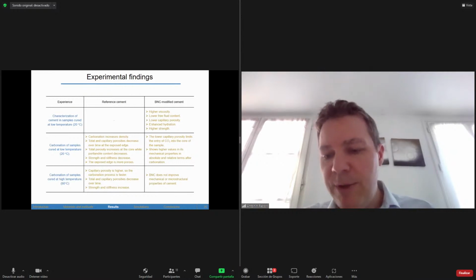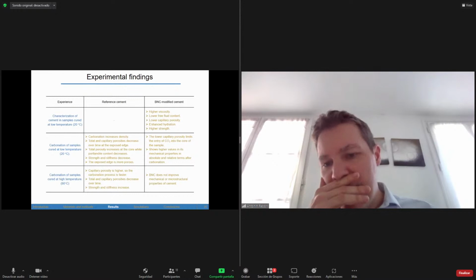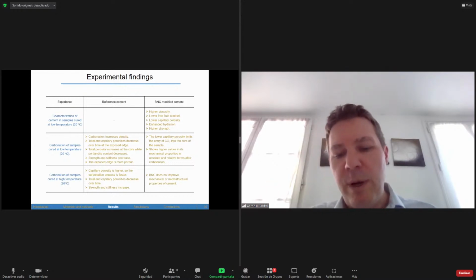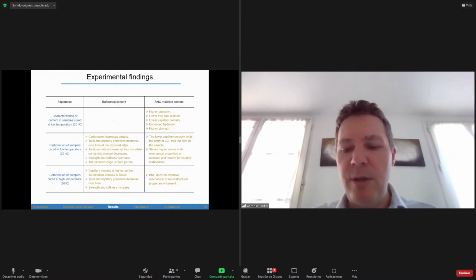But I don't understand two things. So the first thing is, what is the state of the sample in carbonation method B when it is put in the carbonation reactor? Is it saturated or is it dry? Have you resaturated the sample before putting it for carbonation, or is it put dry into the carbonation reactor? All cement samples were fully saturated before putting them in the carbonation cell. So yes, they were put in water before the carbonation test.